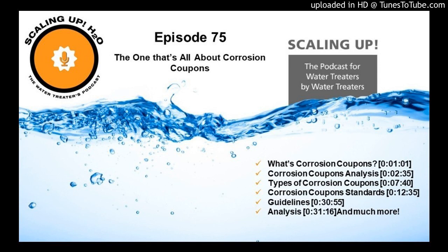Otherwise, you could use a corrosion coupon, and a corrosion coupon is a lot cheaper than that expensive piece of equipment that you are treating. And on a more proactive basis, you can now see what the corrosion rates are within the system. And again, like I said, see if those are acceptable or not acceptable. The great thing about corrosion coupons is they're a shorter interval than whenever that equipment inspection is, so you can make slight adjustments to your program and see if you're increasing or decreasing the effectiveness of the system.